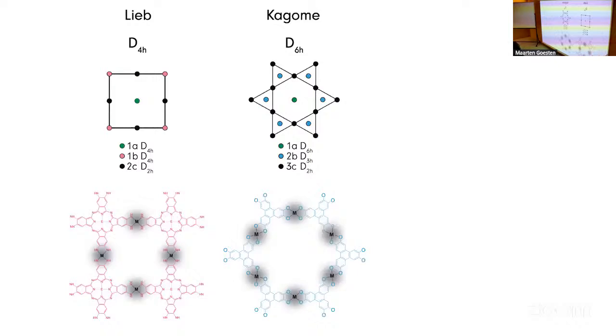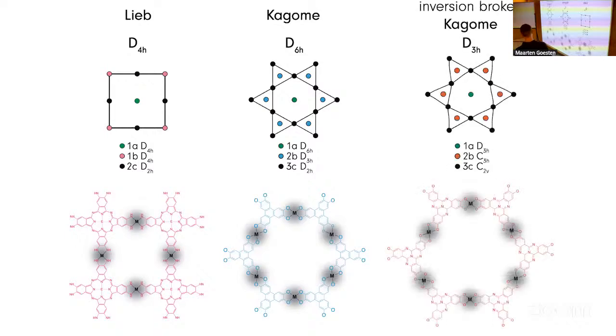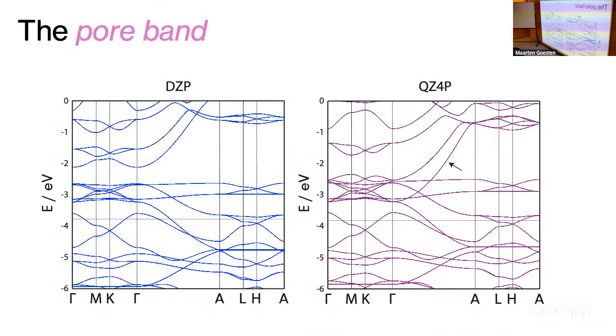What is very interesting is that I've shown you we have this Lieb lattice and this Kagome lattice, but Mircea Dincă recently developed these MOFs where you're using a nitrogen-centered ligand. That nitrogen-centered ligand breaks inversion symmetry. So you get an inversion-broken Kagome lattice, and if you have no inversion symmetry in your crystal, also from space group theory, you will have spin splitting away from gamma. All these things are at this moment not very well understood. So if you give me 5 minutes, I will show you some very preliminary results that we're working on right now.